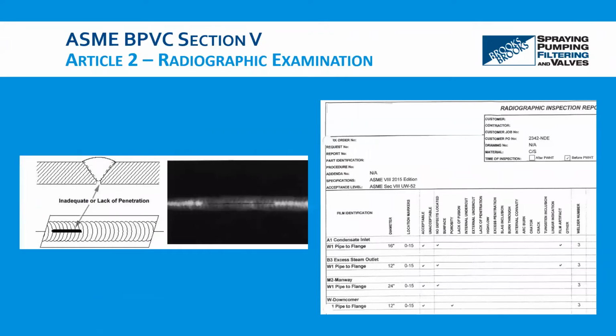And the end result of that X-ray would yield a film such as this. And in this case, the welded joint would not be acceptable due to the film showing a lack of penetration. You can see here as the dark line in the developed X-ray photo. And a report would accompany this as what we have here. Although, sorry, it should be noted that this report is not associated with this film. And it will identify which weld joints are acceptable. And if they are not acceptable, it will disclose why they're not. However, it should be noted that in some cases, it can still be acceptable, even though there are notes here, because it still meets within certain limits that you can still be deemed as acceptable.